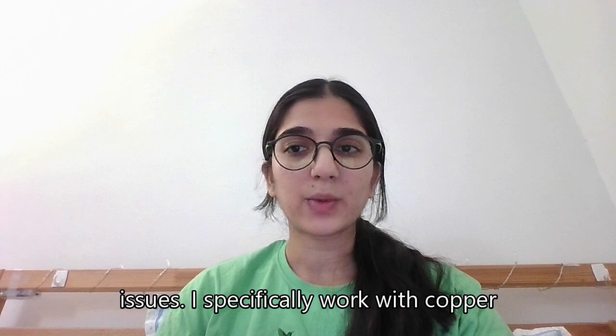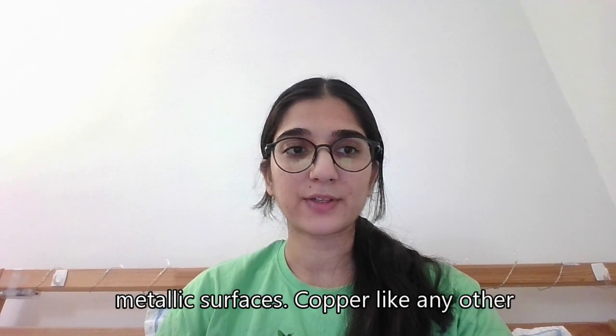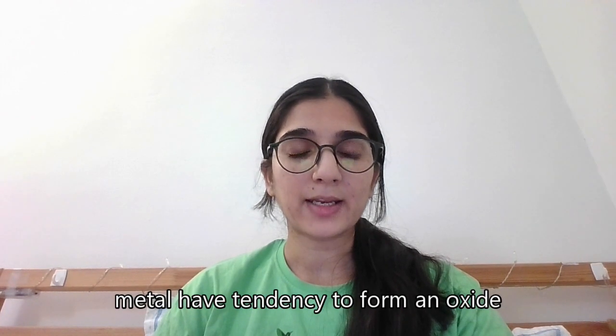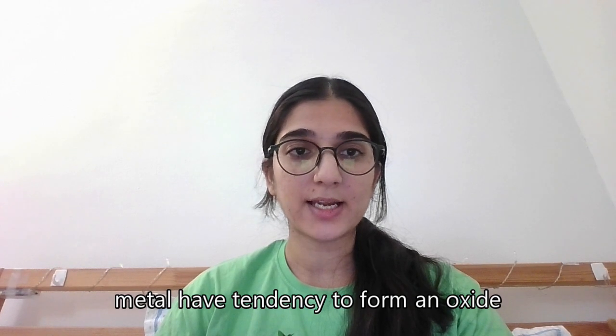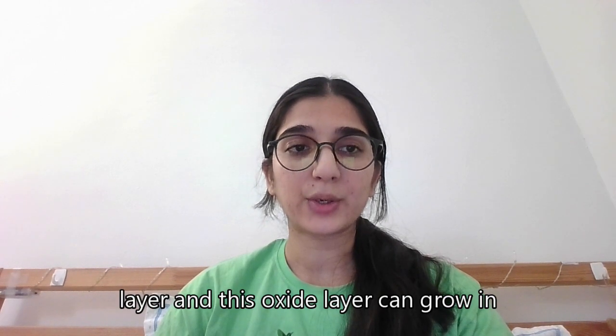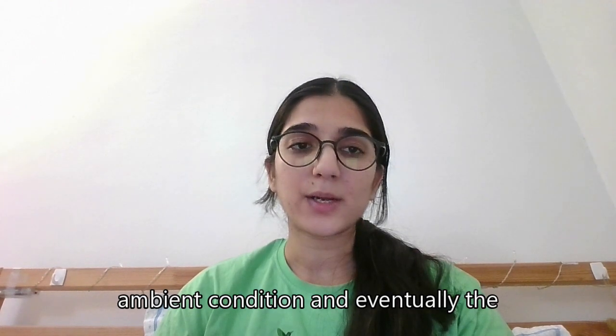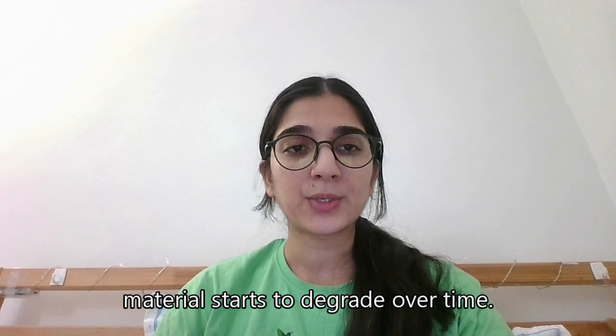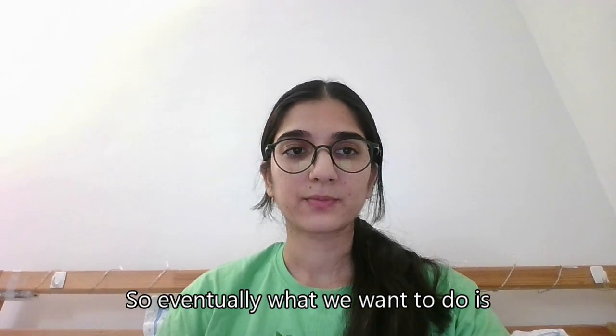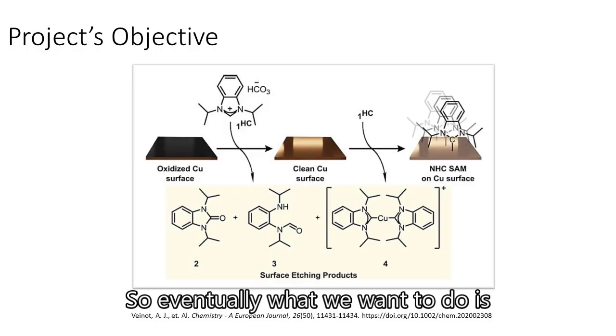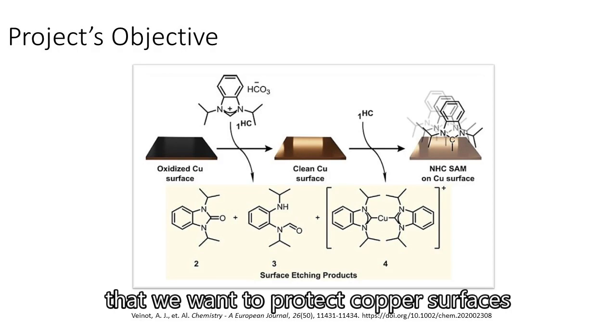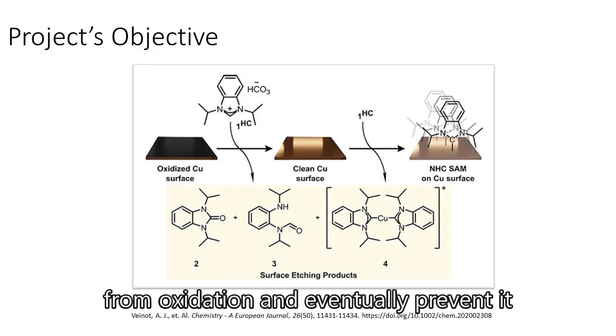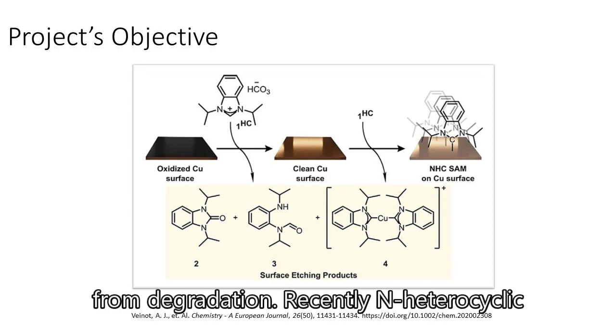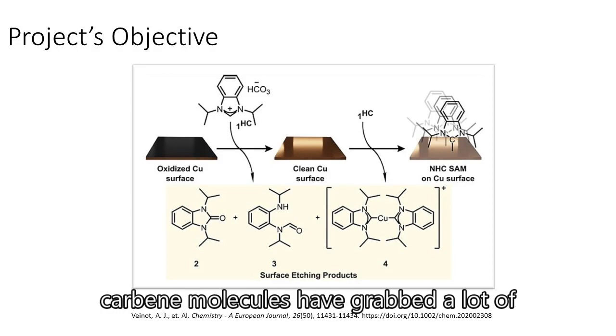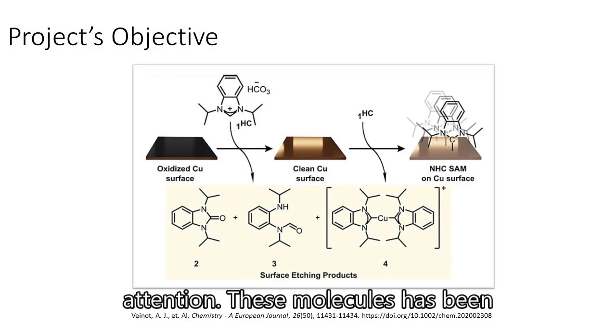I specifically work with copper metallic surfaces. Copper, like any other metal, has a tendency to form an oxide layer, and this oxide layer can grow in ambient conditions, and eventually the material starts to degrade over time. So eventually what we want to do is protect copper surfaces from oxidation and eventually prevent it from degradation. Recently, N-heterocyclic carbene molecules have grabbed a lot of attention.